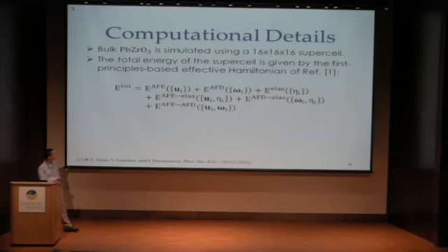In the total energy, we have antiferroelectric energies, which are associated with the local mode; antiferrodistortive energies, which are associated with the oxygen-octahedron tilt about the pseudocubic axis; elastic energies, which are associated with the strain variable tensor; and coupling energies, which come from the coupling of the degrees of freedom.